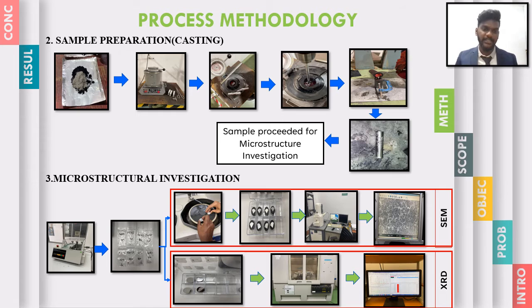And after that, the rolled aluminium was mixed with the molten metal, which was previously melted at 700 degrees Celsius. So the previously melted aluminium was then mixed with the reinforcement material, and straight away it was stirred using the mechanical stirrer for the allocated time of 10 to 15 minutes. After the stirring was done, the molten metal was straight away poured into the permanent mold casting, and the cylindrical-shaped billets were then produced, and the produced samples were carried forward to the microstructure investigation.